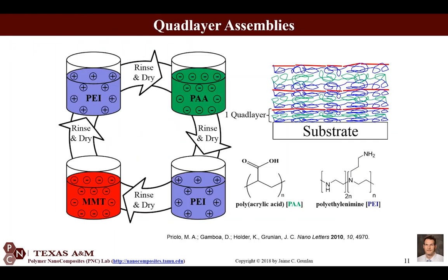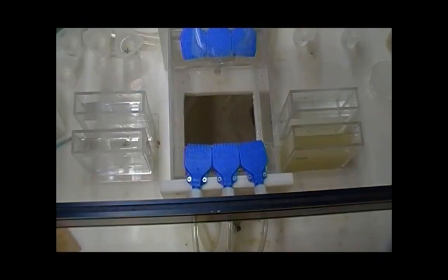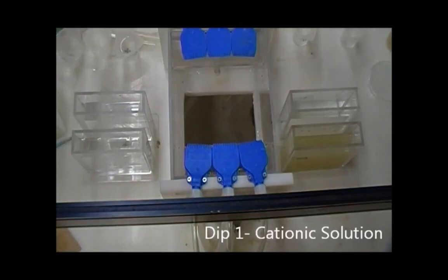And so when we knew that more polymer between the clay in some cases was helpful up to some point, we started to put in more layers. In this case, you're looking at a polyethyleneimine, polyacrylic acid, polyethyleneimine, montmorillonite clay quad layer. Paula referred to it as a tetra layer. They're both cute names, I think, for this structure. But anyway, you can see in my cartoon that it's getting a little thicker with each quad layer deposited.